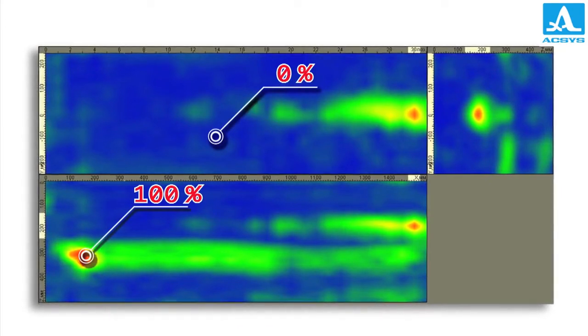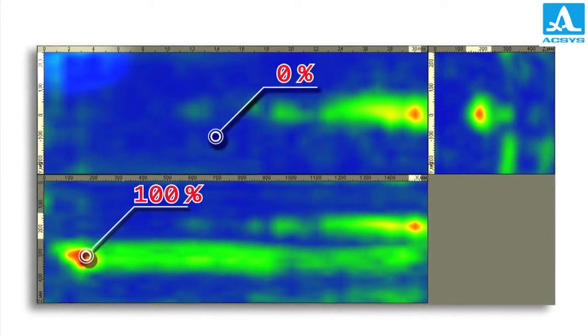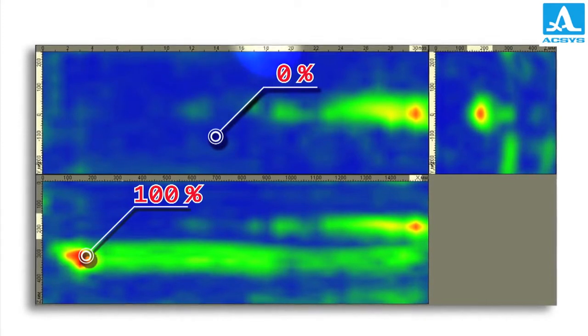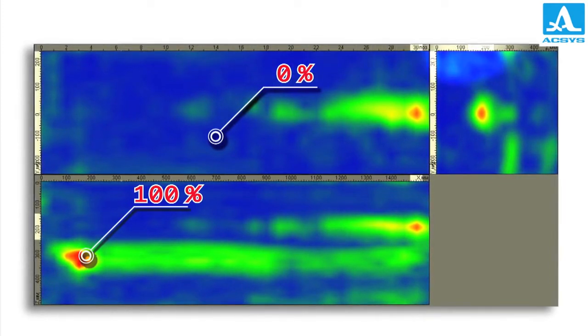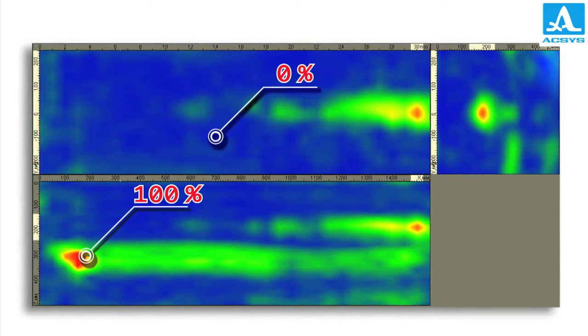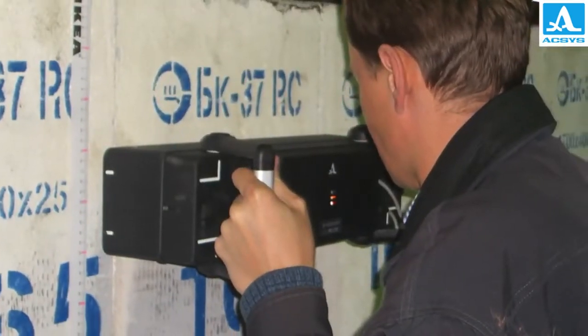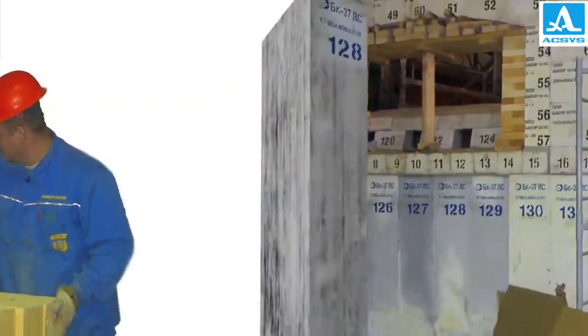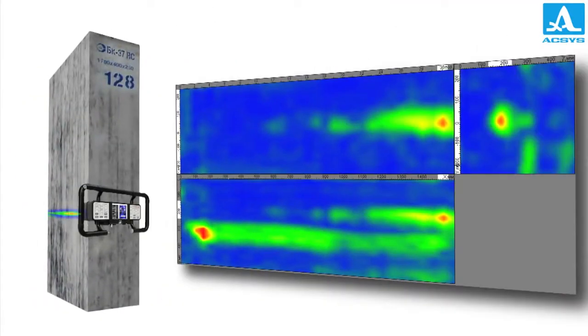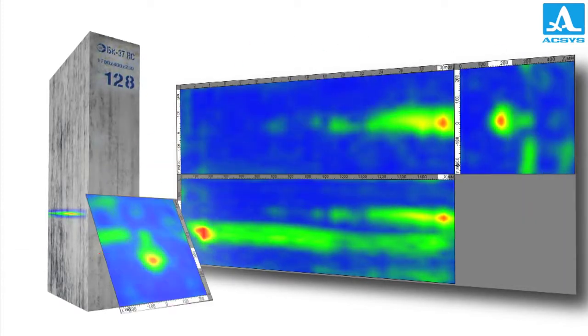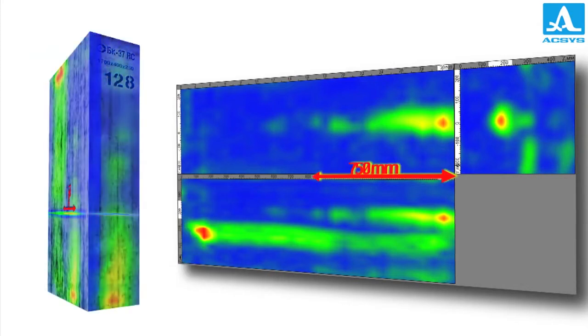Every point in the zone of testing is depicted as a certain color scale, depending on the intensity of its reflection. Every reflector's position can be located with a high degree of accuracy. The tomogram shown was obtained from tests performed on fireproof plates of a glass melter. At a nominal depth of 130 millimeters from the surface, a cylindrical-shaped flaw, approximately 750 millimeters long, can be observed.